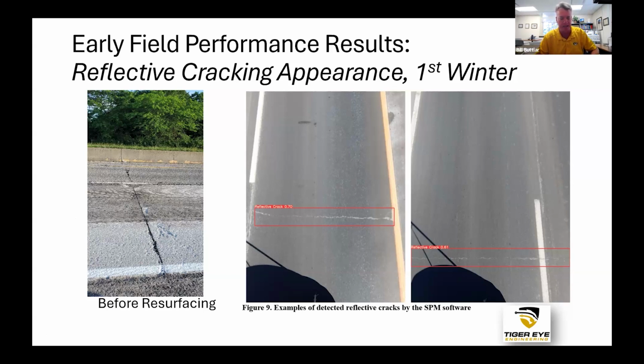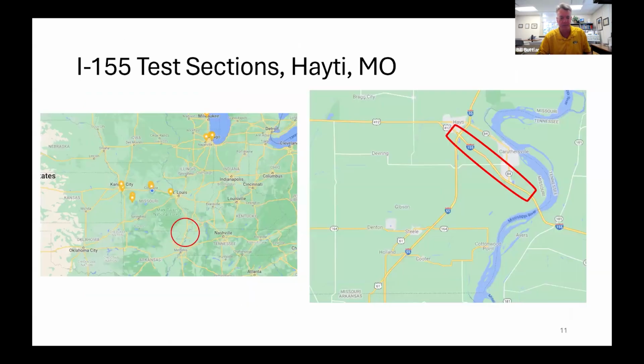So that's what we were given, and it's prone to reflective cracking, as are most concrete pavements. They just sit there and shear and open up and close up with temperature, and they shear with traffic. So we do have a few reflective cracks, but the reflective cracking rates are sort of normal. And we're doing better than the control section, which doesn't have recycled plastics. So, it made a nice thin surface treatment for a little bit of a concrete life extension in this case. No ruts. Yeah, it's performing well.